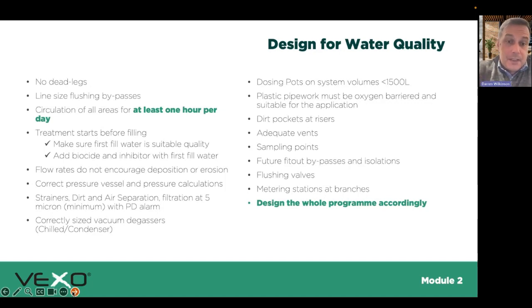Make sure the flow rates do not encourage deposition or erosion. So typically we want to be above 0.5 meters per second, and we don't want to be above the CIBSE guide in terms of maximum flow rates per pipe diameter. Make sure we've got the correct pressure vessel. Really important. I see many system failures, and then it turns out the vessels themselves haven't been sized correctly. And of course, when the system's operating, it starts drawing in oxygen.